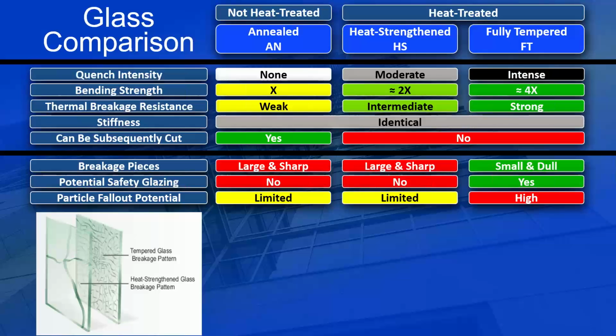Shard retention. So back to that image there in the bottom left corner. Fully tempered glass, also known as safety glass, as you're very familiar with, breaks into lots and lots of very small kernels. Heat strengthened glass does not break into the same pattern. Heat strengthened glass instead breaks closer to that of what annealed glass does. So if there is breakage, tempered glass without an interlayer can fall out of the window opening. Heat strengthened glass, yes, it can fall out, but typically that breakage pattern propagates to the perimeter sealant, which holds those shards of glass in the frame.